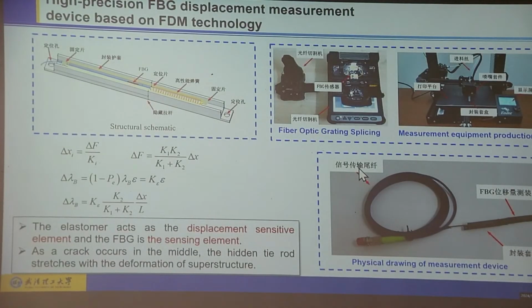But this fiber optic sensor cannot be used directly because it can only measure strain and temperature. In geotechnical engineering, we are more focused on displacement or deformation. So how do we measure deformation based on FBG, fiber Bragg grating sensors? We developed this device, which was developed by our team. We want to measure the cracks or the deformation between this point and this point. If you measure two points of a crack, you cannot directly use an FBG sensor, because the FBG sensor is very fragile. It can be damaged, and it cannot measure very large relative deformations. So we developed this device.